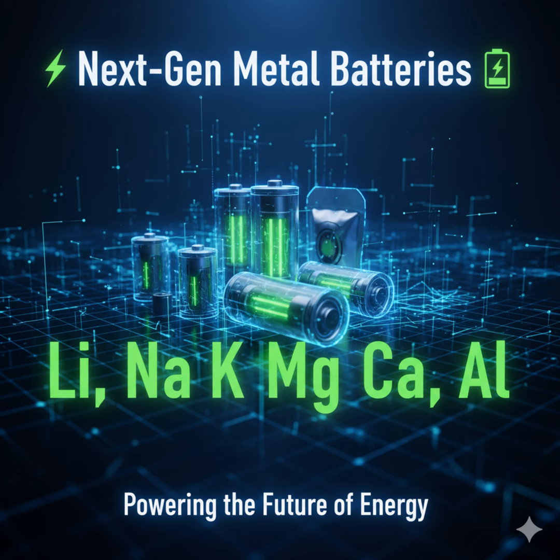Yeah, or creating artificial SEI layers before the battery's even assembled. For lithium, sodium, potassium, since they need mechanical toughness, researchers are adding things that form robust inorganic components like metal fluorides, LiF, NaF. These have wide band gaps, good electron insulation, and high stiffness. Like adding ceramic reinforcement to the SEI? Pretty much. Sometimes they pair these hard inorganic components with flexible polymers, like PVDF, creating a composite bilayer SEI, something that's both tough and can flex a bit with the metal's volume changes, like a flexible suit of armor. Okay, armor for the monovalents.